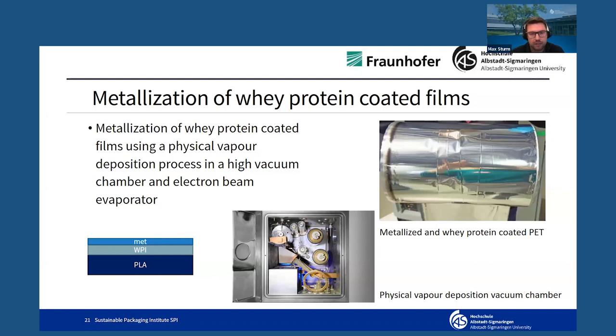At industrial scale, it's also common to use a metallization process for this. And so this was also researched in the PRESERVE project by the Fraunhofer IVV. Here, the metallization layer was applied on top of the whey protein coating with the substrate film below. This has also the benefit of allowing the enzymatic removal of the whey protein, so the metal layer can be separated from the plastic layer, here in this case, for example, PLA. So the PLA can be reprocessed at end of life. The first trials here showed very promising results.